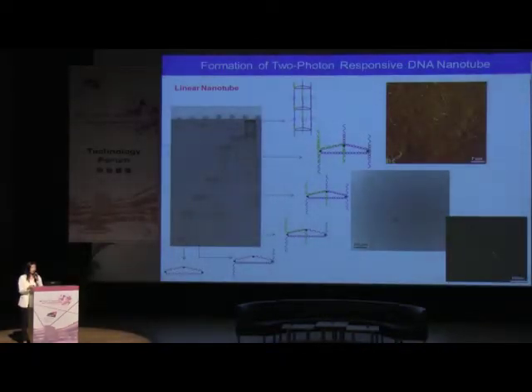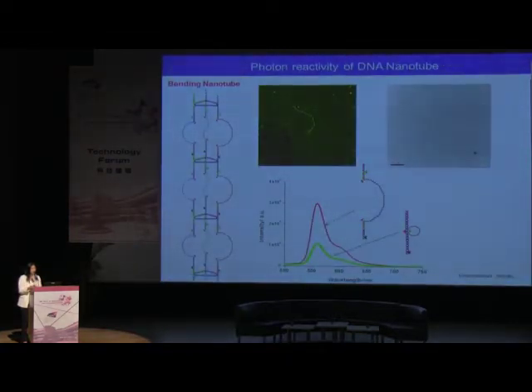So we're using a similar approach to generate this linear nanotube with a long tubular structure from different characterizations. Our preliminary result found that after the excitation, our nanotube becomes a bending nanotube with some degree of curvature, from the confocal and also the TEM study.